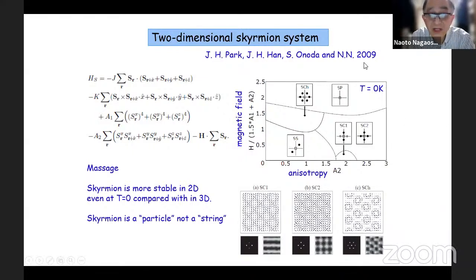And actually around that time, we were considering the two-dimensional model with the Dzyaloshinskii-Moriya interaction and also the spin anisotropy in the plane of a magnetic field and anisotropy. And we have a variety of crystal structures of spin textures. Here is a skyrmionic phase, a triangular lattice of the skyrmion, and also the square lattice or one-dimensional structure of the skyrmion, derived theoretically by the Monte Carlo simulation.